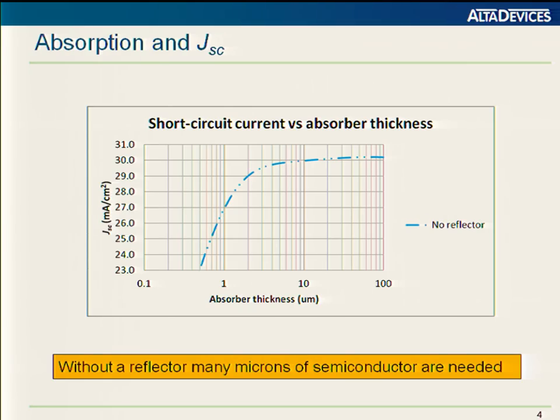Now, using a very simple optical model that just considers a slab of semiconductor material, which has some reflection at the interfaces, some loss mechanism within the cell, we can then think about JSC, the short circuit current density, as a function of the thickness of the cell. So as you'd expect, it's roughly exponential up to a point where you become somewhat limited by carrier transport due to loss mechanisms.